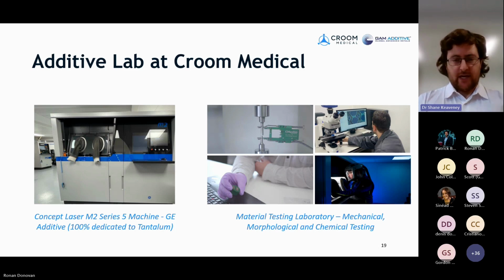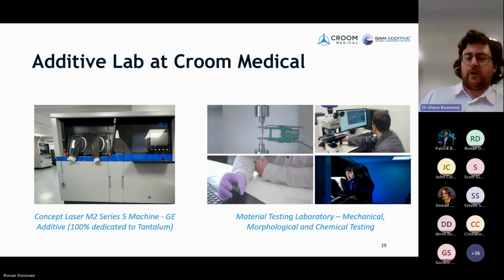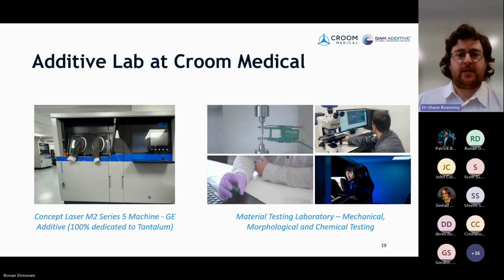So for instance, mechanical testing, mounting and polishing to look at the microstructure evolution, investigate our heat treatment, density, and also analyze our powder characteristics in terms of how they're changing over time, which I think is a very key piece, especially for additive manufacturing through SLM, where we're working with the powder. So the powder obviously is one of the variables in there, and it needs to be monitored, but also the results of the printing need to be monitored very carefully. So that whole side of quality control through our material testing lab has been quite key, and obviously key to the development here with tantalum.